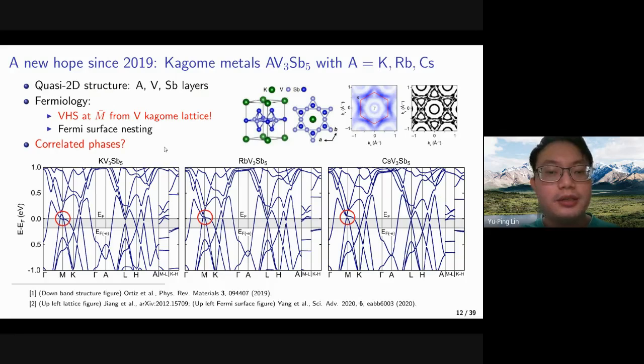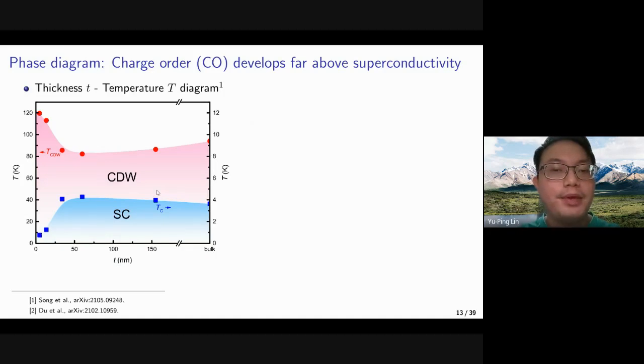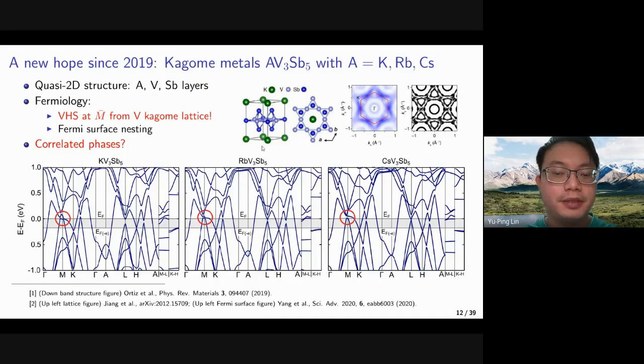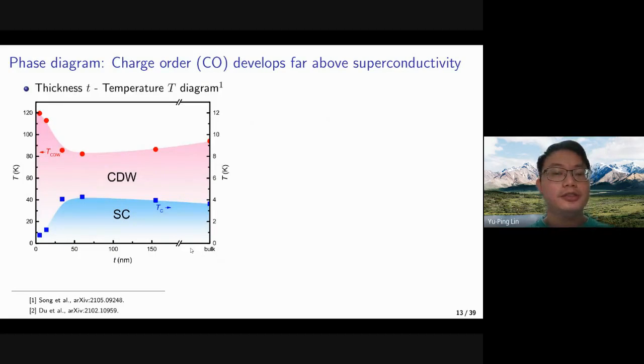So the question is, what are the correlated phases that were observed in the experiment? People have found that in 3D, because we have some layer structures, the material is essentially a 3D structure, although the structure is quasi 2D because we have layer structure. If we are looking at the bulk material with a finite thickness, we find that the superconductivity develops at lower than 4 Kelvin, but the charge density wave can already develop at around 90 Kelvin. And you can see that if we lower the thickness, the superconductivity vanishes in the 2D limit, but the charge density wave can become stronger.